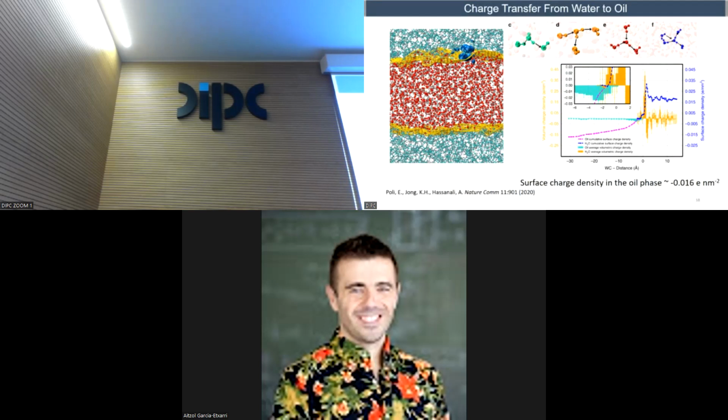That's what makes the oil droplet surface negatively charged. And at this point, our theory collaborator, Dr. Alessandro Hassanali, was already working on this theory, and they had shown, using ab initio MD simulations, that they calculated the charge density of individual layers, and they were able to calculate that there is a negative charge density that seeps into the oil.